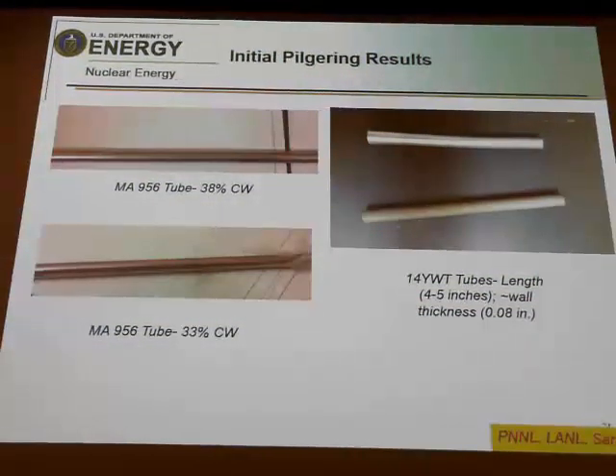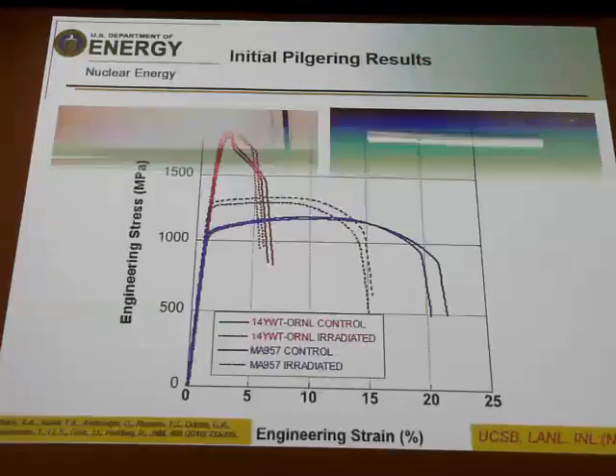And through working with Sandvik, through collaborators at Pacific Northwest National Lab, they have been successful in Pilger processing MA956. So that's a FeCrAl ODS, an iron chromium aluminum ODS, and there it doesn't have as fine of an oxide dispersion. So we started with that as something to sort of test the process with. They were successful with that. We've done some short lengths of 14YWT, but we're not there yet for longer, thinner walled tube.